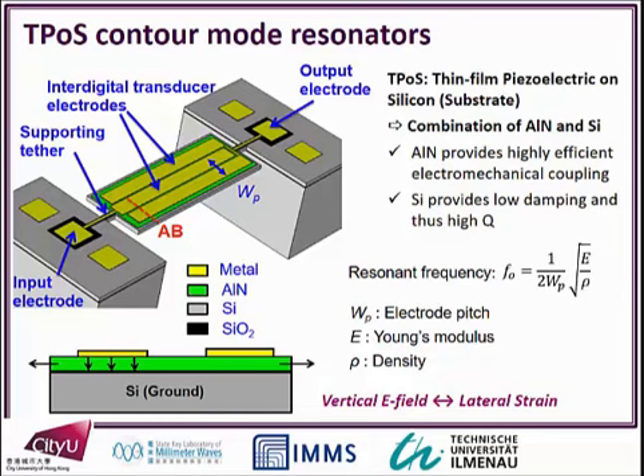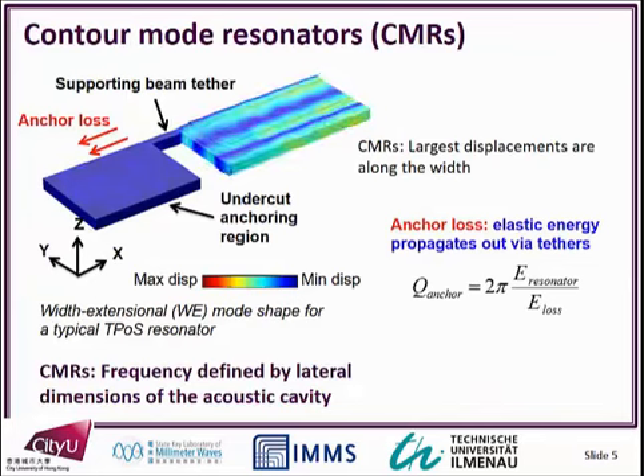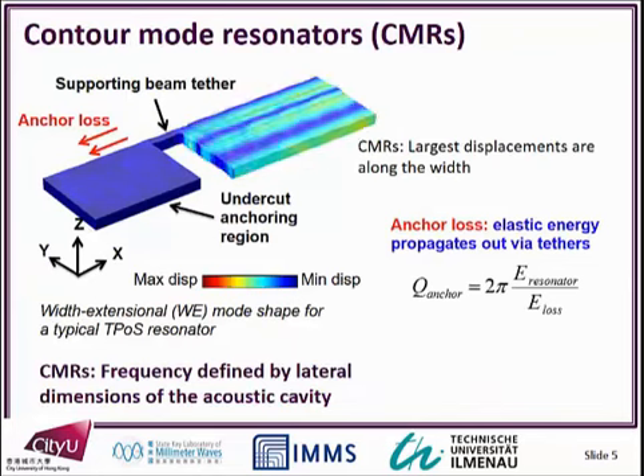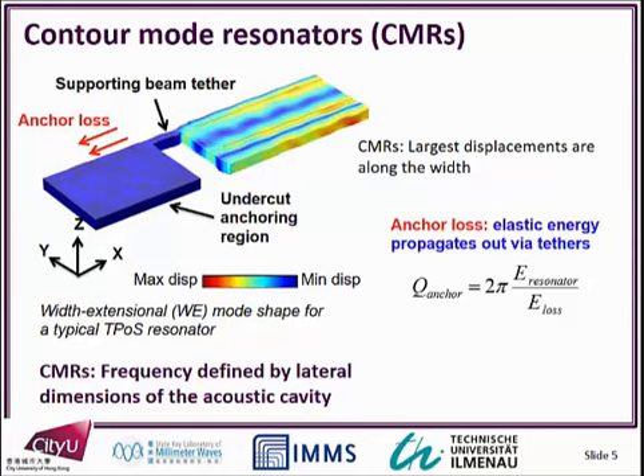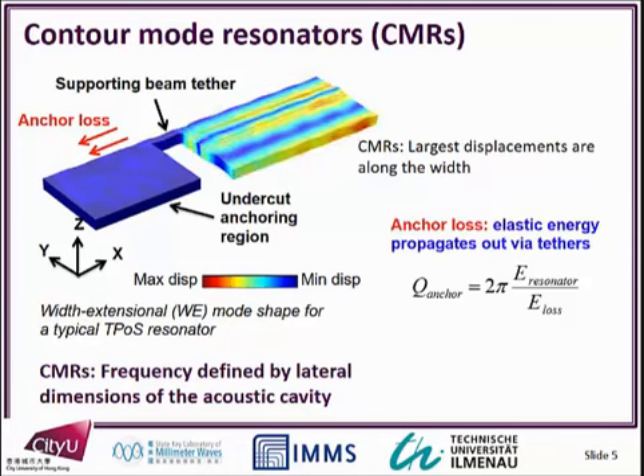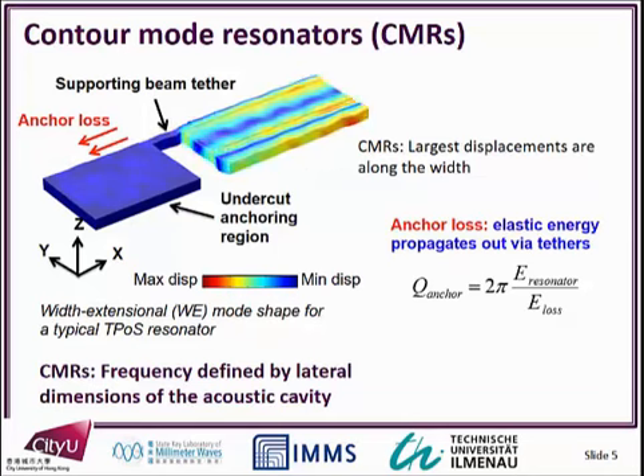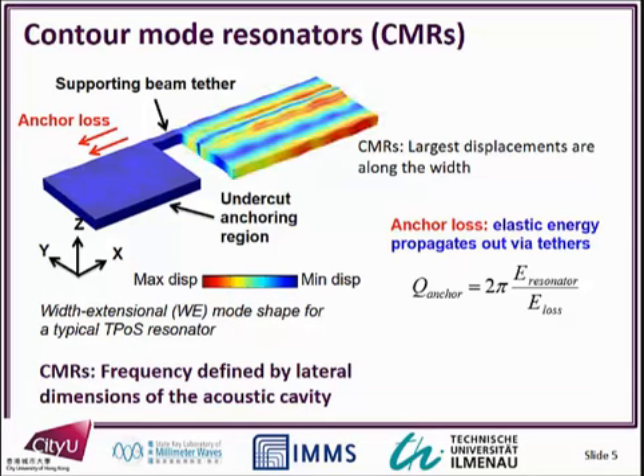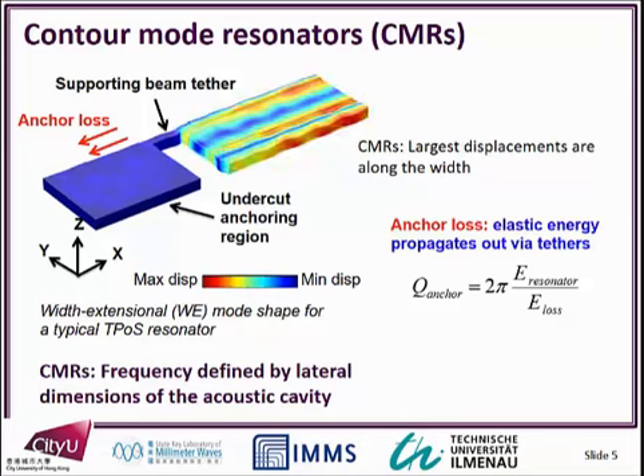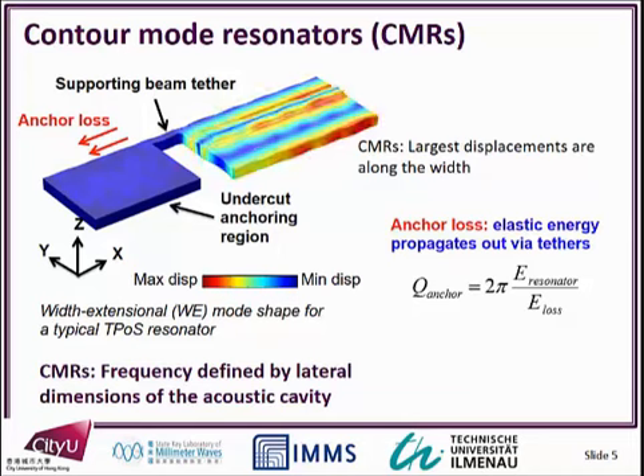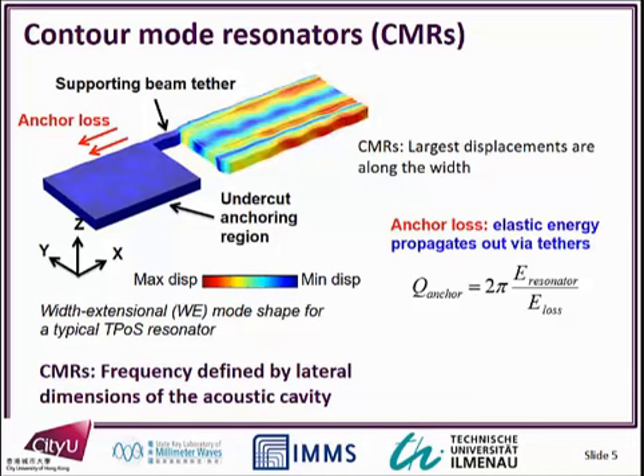With TPOS, as I mentioned before, it's a combination of aluminum nitride and silicon. You've got high coupling efficiency from the aluminum nitride, and the silicon provides low damping. The frequencies with these are defined by the pitch width of these electrodes. So contour mode resonators are defined by the lateral features, so it's vibrating in plane itself. I have to emphasize that these are in-plane modes primarily. And you've got to clamp them somewhere, as we've seen in the previous talk. That gives you a physical connection as well as an electrical connection. And one of the losses is really coming through the anchors themselves.